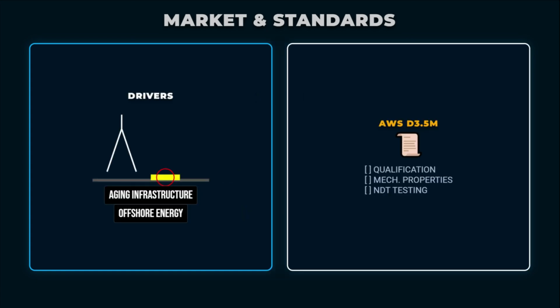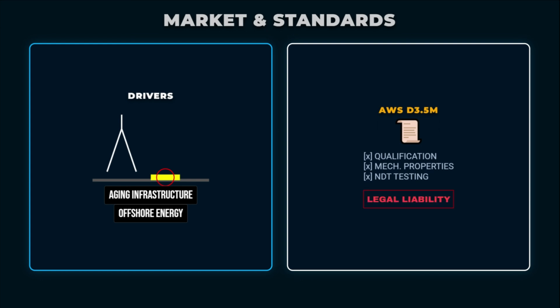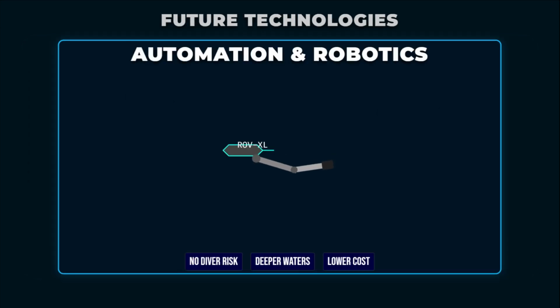Regulatory compliance is governed by international bodies and national standards, with the American Welding Society D3.5M specification being a key industry benchmark for underwater welding. This standard dictates the qualification procedures for welders, the acceptable range of metallurgical properties for the weldment, and the non-destructive testing methods required. Welders must pass specific performance qualification tests, often conducted in hyperbaric chambers simulating operational depth, to certify their ability to produce sound welds under pressure. Failure to adhere to these standards results in immediate project shutdown and significant legal liability.